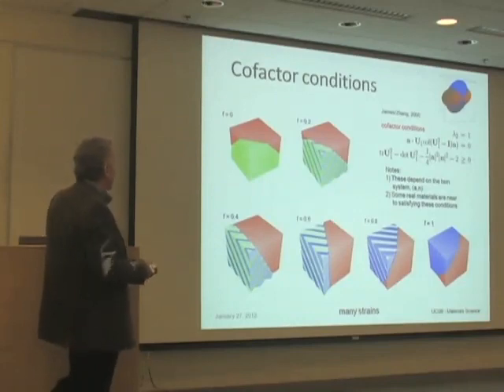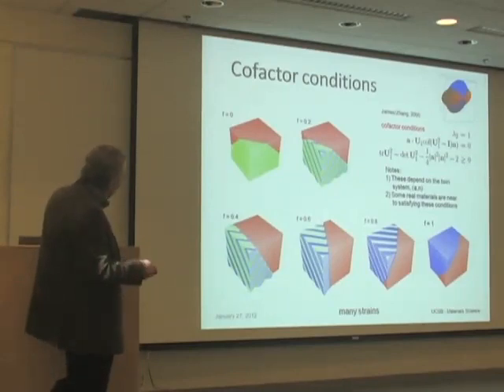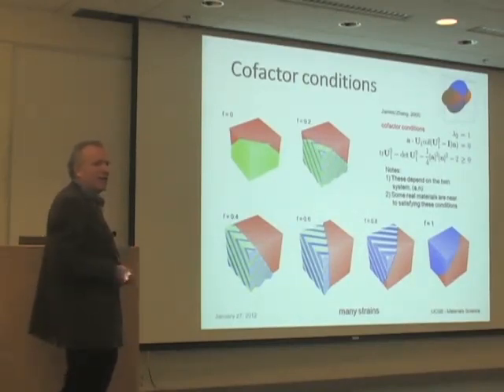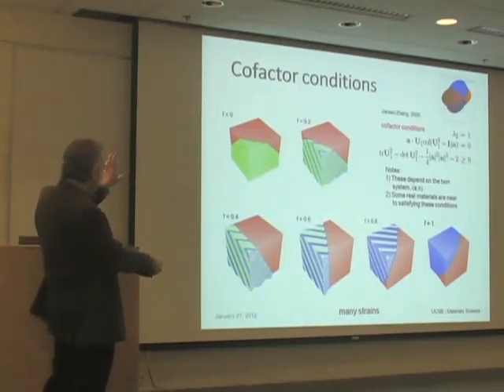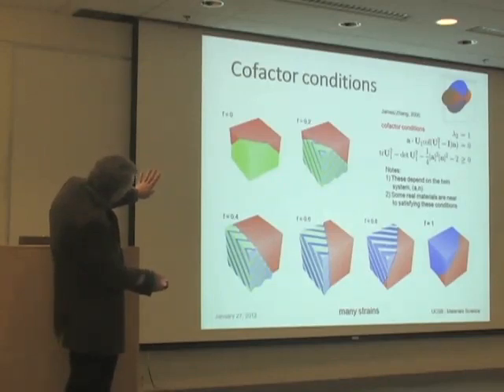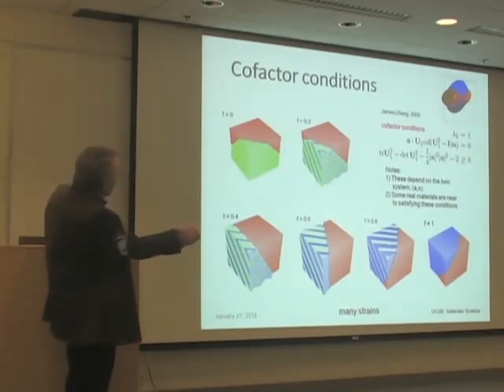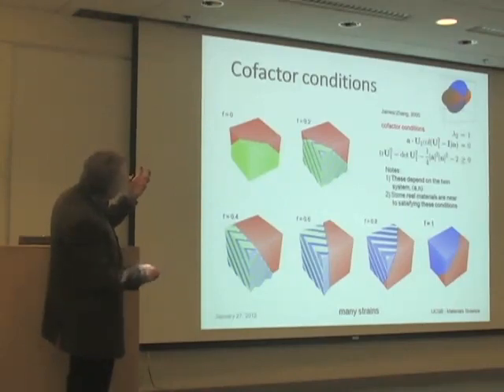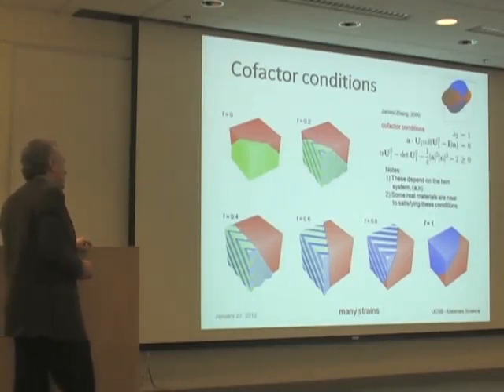And if these cofactor conditions are satisfied, not only do you, of course, since lambda 2 is 1, have the perfect interfaces between austenite and martensite for both the green variant and the blue variant. But in addition, you can continuously vary the volume fraction. And each of these interfaces is a low energy interface in the sense of the crystallographic theory. So there's a whole bunch of strains. This is compatible even though it strains a lot as you change the volume fraction. In fact, I drew up here the strain ellipsoids of the starting state and the ending state. So it's as if this ellipsoid gets continuously strained into this blue ellipsoid. So you know, there's a remarkable degree of compatibility here and presence of many, many strains.